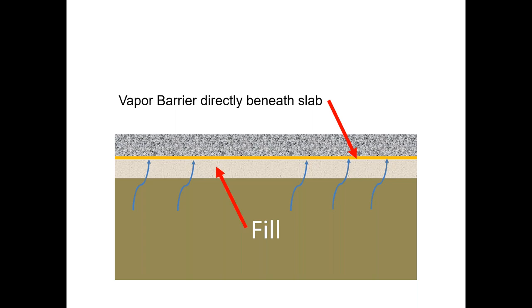Yes. Okay. Changing the location of the barrier doesn't help the problem of slab hydration if curing water is trapped against the bottom of the slab by the vapor barrier. Two issues happen. The curing conditions of the surface and the bottom of the slab are different and thus cure at different rates. This can create curling issues. The challenge of urgency to occupy the slab drives the curing compound or membrane, et cetera, at the surface, even if trying to control cracking, which traps the moisture in the slab.